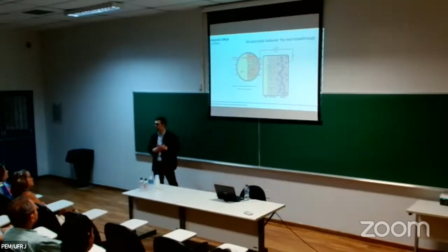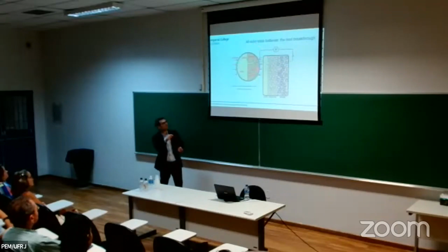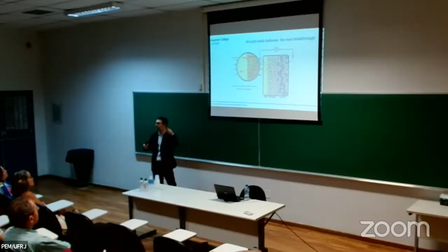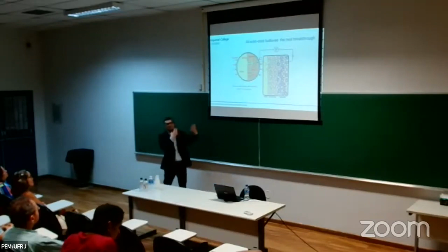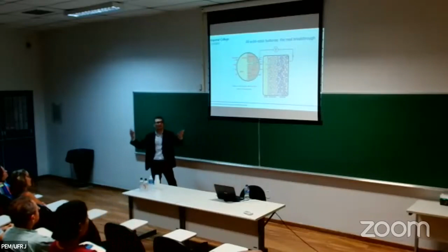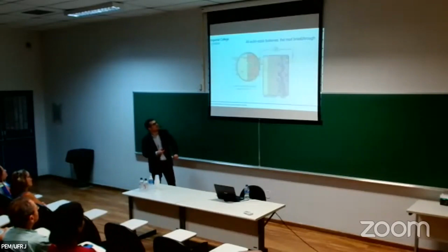There's a lot of effort going into this direction, commercializing these solid-state batteries. But the reason why we don't have commercial solid-state batteries yet is because we have these mechanical instabilities happening at the interface between the lithium metal and the electrolyte. You can see here we have cracks, we have wetting here, and the biggest problem is these dendrites. These are needle-like structures of lithium that will start growing at the interface between the anode and the electrolyte, and they will grow all the way into the cathode, and they will cause the short circuit of the battery. So we need to be able to understand these mechanics problems in order to achieve this big breakthrough in battery technology. So let me tell you a little bit of how we did that.